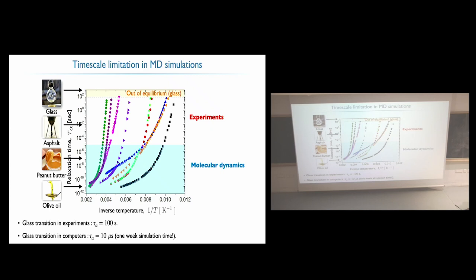And you could say, well, great, since the glass transition is defined arbitrarily, my arbitrary decision for computers is here, and this is fine. But actually, it means that you're not able to observe how the liquid slows down 6 orders of magnitude more. You can investigate what's going on here, but this regime is not accessible, and this is really where it starts to get interesting.